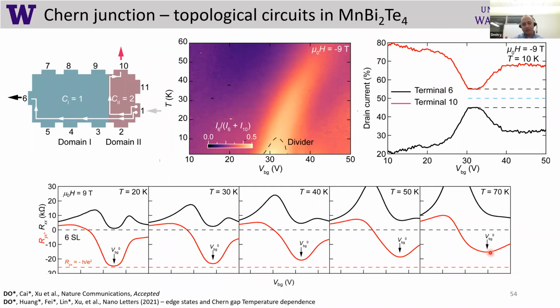It's not a fully quantized system per se. Maybe the bulk is leaking, there are some defects, but still it's surprising that in manganese bismuth telluride, we can see very large RXY signals up to really liquid nitrogen temperatures. So in this case, it's kind of the same. I outlined the divider here by using 10% variation. Actually, sorry, 5% variation. So we can do line cuts in this map and see that perfect behavior would be 50-50. Now we have essentially 55-45, but the effect is still there and it persists up to 60 Kelvin in this particular map, which is very promising.